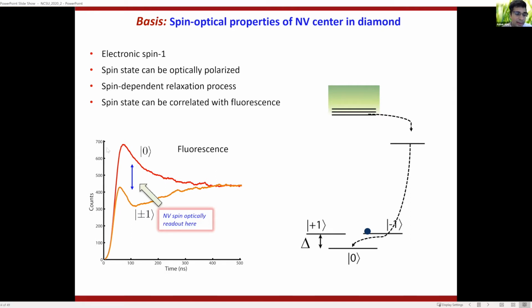So when you look at the fluorescent counts, starting from 0 or -1, you get lower fluorescent counts if you start with -1, just because with some probability you go through a state that's non-radiative, and so it does not produce any fluorescence. But a second very important property is the singlet state selectively relaxes only to the ms equal to 0 and does not come back here. If you start with the ms equal to -1 state, you go through this path, but you finally land back in this ms equal to 0 state.